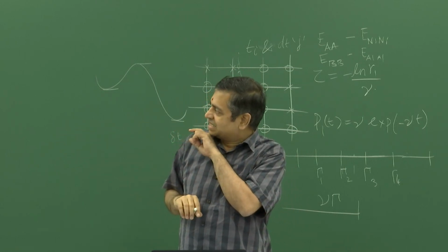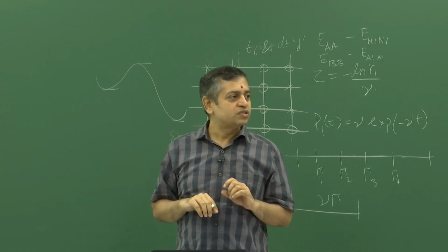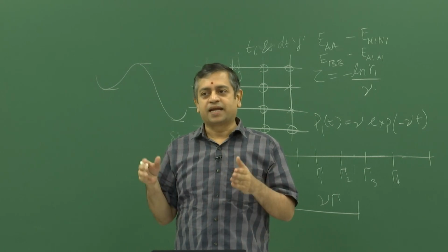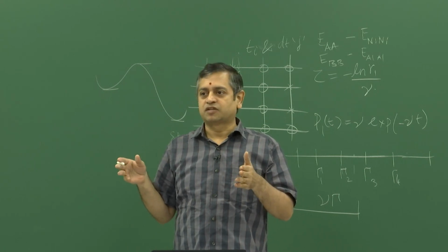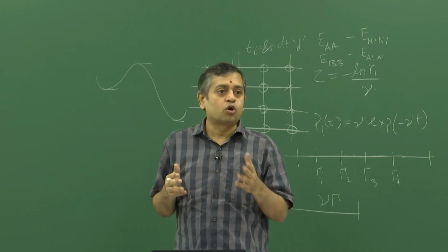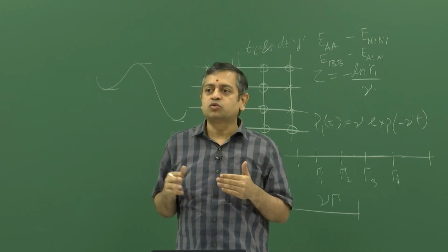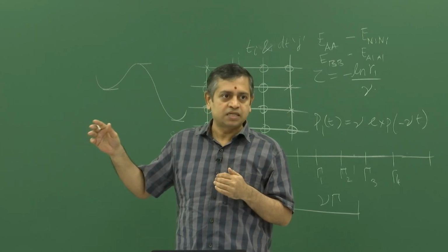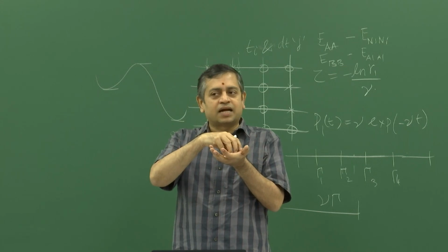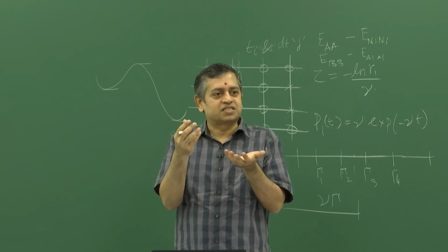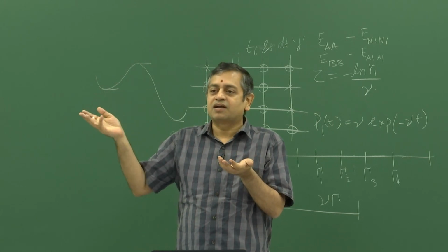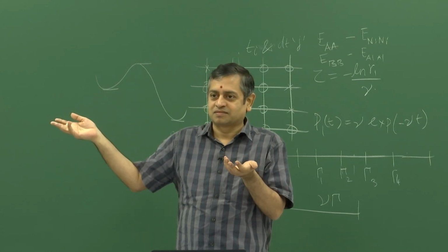But there is a trick here. If you just consider the vacancy formation energy to be the energy required for breaking all the bonds, you get more than what you would actually see in a real system. That is because you break the bonds, take one atom, and that atom does not disappear from the system. It goes and sits on the surface where it can recover at least 50% of the bonds.